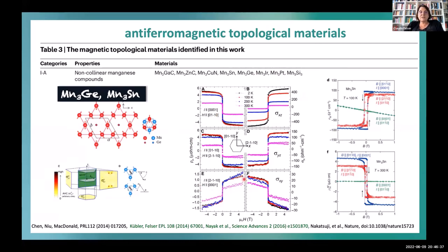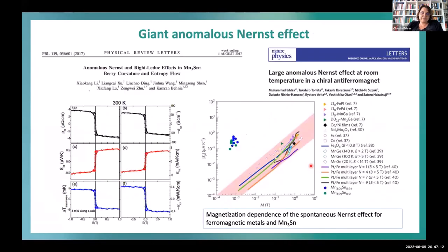He and his co-workers in our group grew the crystals, and he saw this very nice anomalous Hall effect as expected from our calculation. Again, Ajaya might remember, we discussed this with Stuart, and Stuart said, no, Ajaya's samples are dirty, I don't believe this. Finally, Nakatsuji published this Nature paper, and we had been sitting for a long time already on this data, so Ajaya's paper went into Science Advances, since we had the germanium compound and Nakatsuji's tin compound.